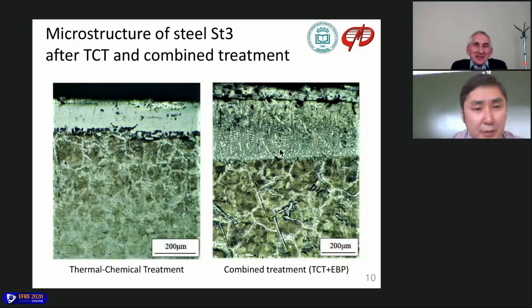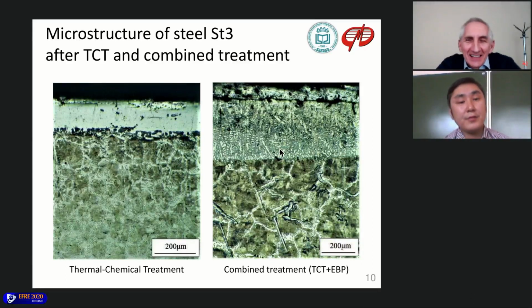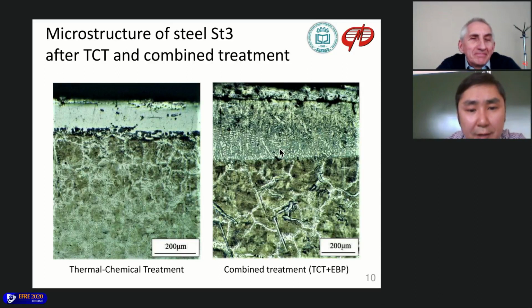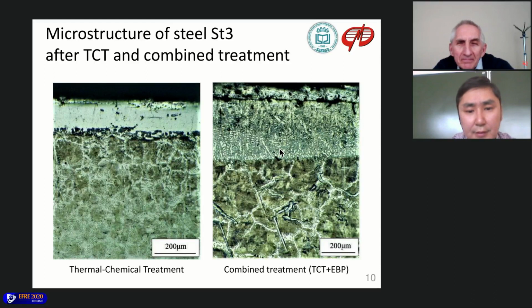And subsequent electron beam processing of this diffusion layer resulted in huge transformation of the layer. After that, we obtained light dendrites in the structure, so the thickness of the layer increased by 2 times, and also you can see that base metal microstructure changed. So the crystals or grains of the base metal, so the EBP process resulted in coarsening of base metal grains.